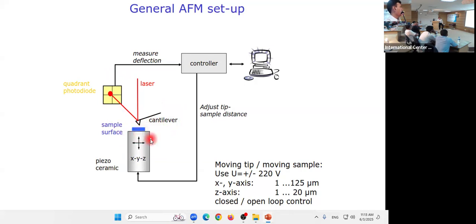Once you load your material here, what happens? This is the cantilever, which is attached to the sample holder, and it will just scan, start here, move through, and go back and forth. In that process, you see that there is a laser coming on, but that laser should be right in the middle of the tip of the cantilever, so that once it moves, the deflecting light, at the beginning, should be in the middle.